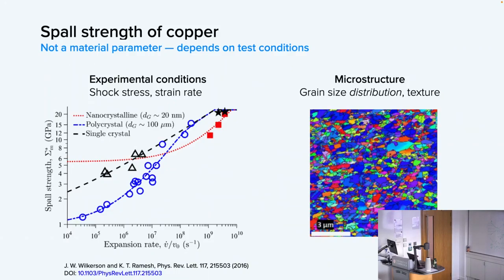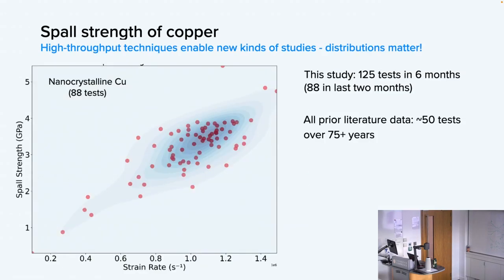The point I want to make here is that the experimental conditions matter. So the shock stress matters, the strain rate matters. In our experiment, those two things are linked. But the other thing that matters, of course, is the microstructure of the material, and not just the average microstructure, but the grain size distribution and how that grain size distribution varies from place to place. Because the scale of our experiment now has been shrunk so much, now we're looking at a region which is maybe a millimeter in diameter and a couple hundred microns thick. Now you're starting to sense some of the statistics of the microstructural variation as you go from place to place on this foil. Things like texture also vary and are also important.